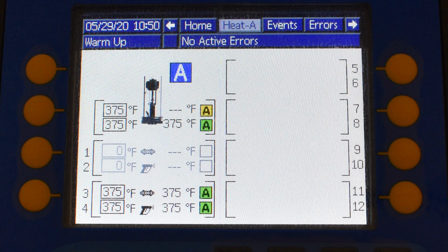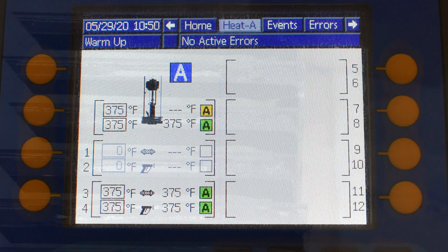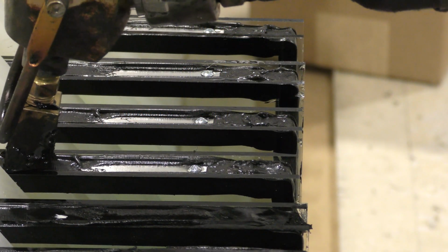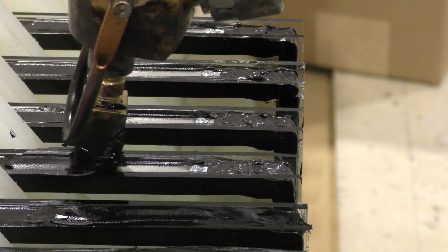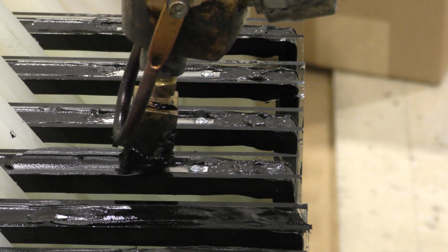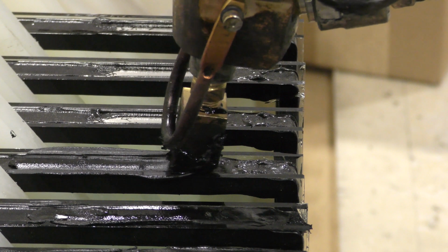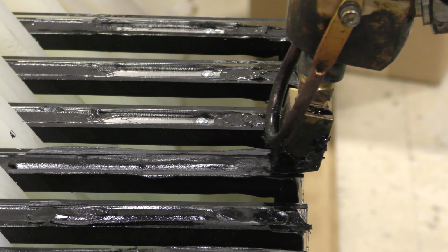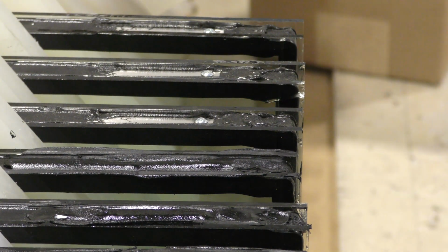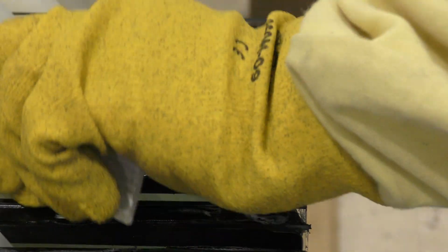Ensure that the patch sealant is at the recommended application temperature. Depending upon the type of patch pump, it may take 30 to 90 minutes to warm up and stabilize temperatures. The temperature of the sealant used to patch the fourth corner must be high enough to remelt the sealant on the IG unit to create a bond between the two materials and to the glass and spacer materials. Consult the sealant manufacturer for specific process parameters.